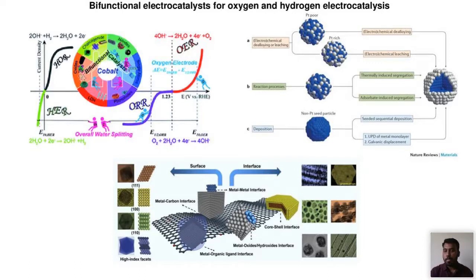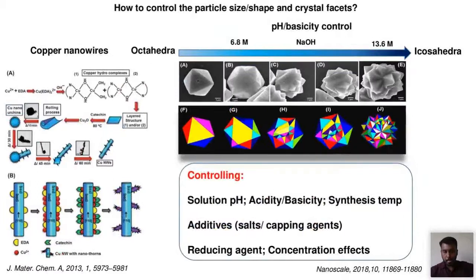This can also lead to improved kinetics. And surface engineering and interface engineering are also playing a major role. You can use metal oxide or hydroxide and metal organics based substances. How to control the particle size, shape, and crystal facets? There are several ways to control the shape and size of a particle and crystal facet. This can be done by adjusting the solution pH, acidity and basicity, and synthesis temperature, and also capping agents.